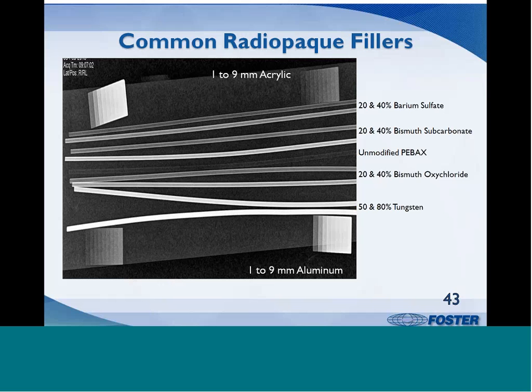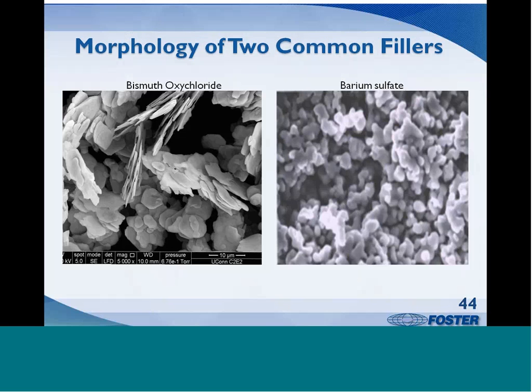The corner blocks are aluminum and acrylic step blocks to help gauge the effectiveness of the fillers. In this case, 20% barium sulfate is equivalent to 1 millimeter of aluminum, and 80% tungsten is more effective than 9 millimeters of aluminum. The fillers come in several morphologies. Most are small, irregular particles made by milling larger particles, and that would be representative of the barium sulfate. Bismuth oxychloride is unique with its plate-like structure, which gives rise to a level of pearlescent effect in the final part.